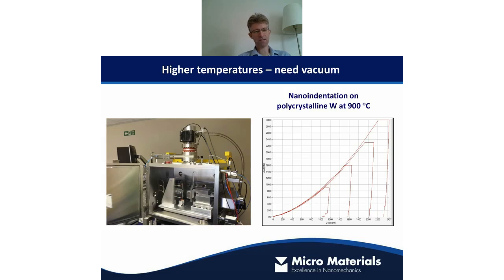So when you want to go to higher temperatures, it's really a good idea to go to vacuum. This protects the indenter from oxidation wear, but it also protects the samples from oxidation. It allows you to test samples such as tungsten, which readily oxidizes above a few hundred degrees and forms a very thick tungsten trioxide on the surface. And this is a Nanotest Extreme system, slightly different to our standard system, but the same basic principles.